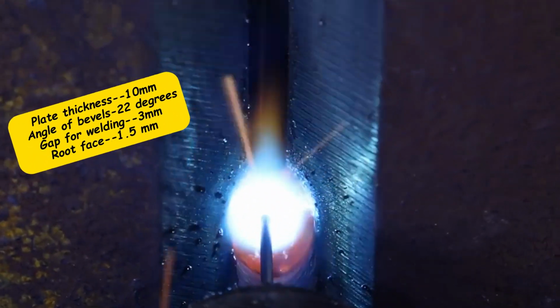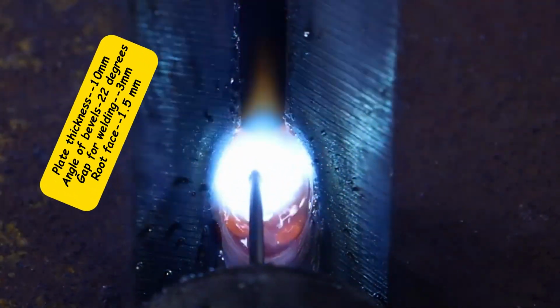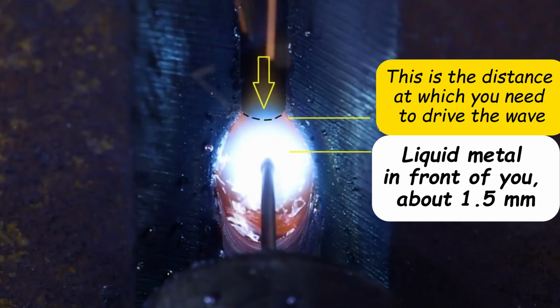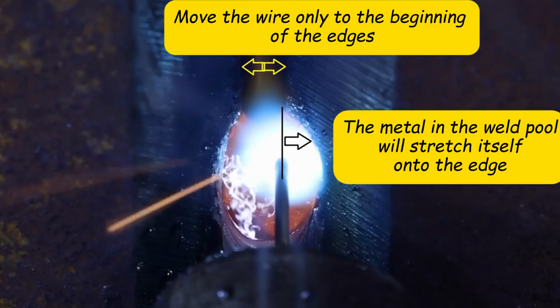We will use plate thickness 10 millimeters, angle of bevels 22 degrees, gap for welding 3 millimeters, and root face 1.5 millimeters. This is the distance at which you need to drive the wave of liquid metal in front of you, about 1.5 millimeters. Move the wire only to the beginning of the edges. The metal in the weld pool will stretch itself onto the edge.